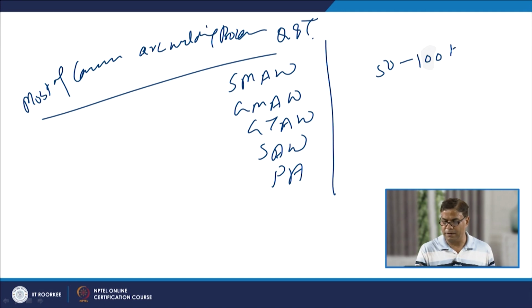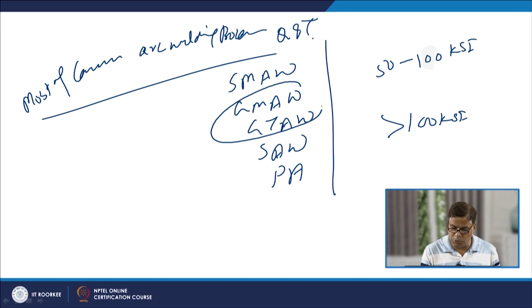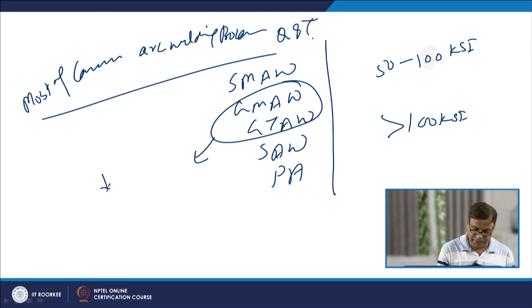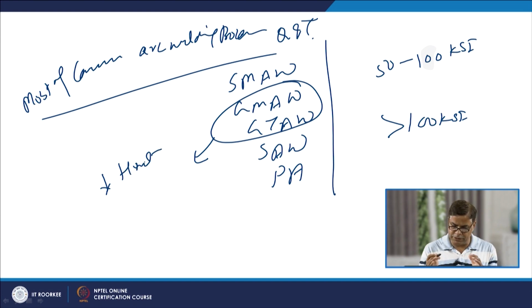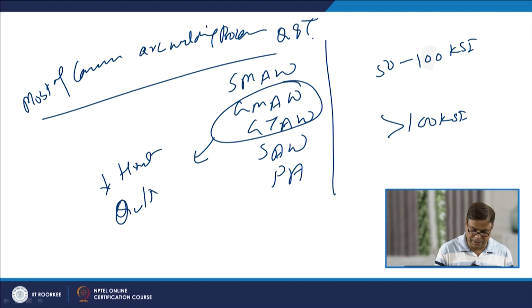All these can be used for welding of all types of steels having strengths from 50 to 100 KSI. This is a very general statement, but when the steel strength is greater than 100 KSI, we would like to use those good quality welding processes which offer lesser heat input, so that the heat affected zone being formed is limited. At the same time, the oxygen and nitrogen concentration in the weld is also less.